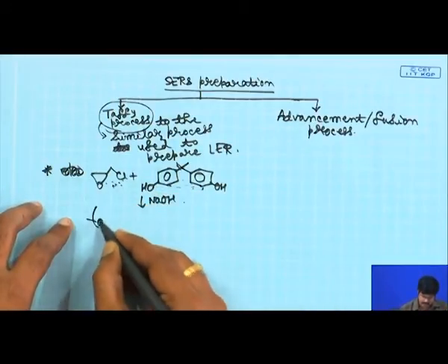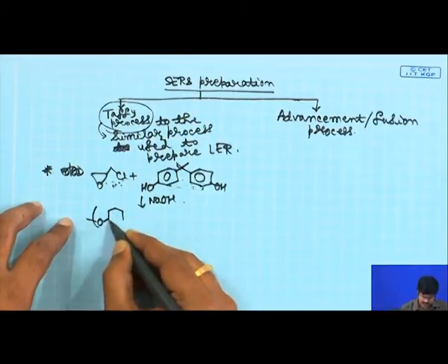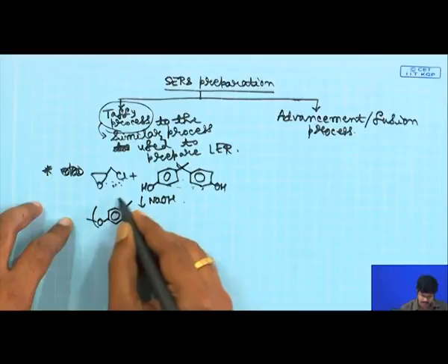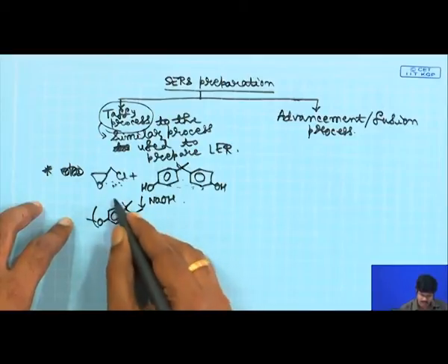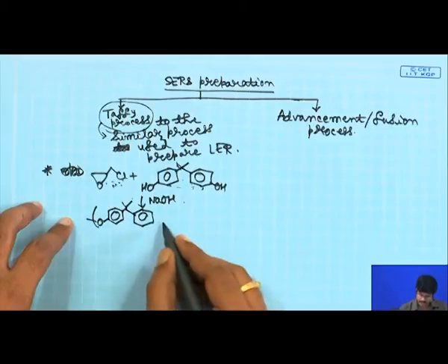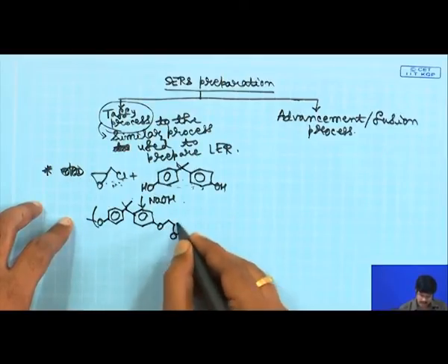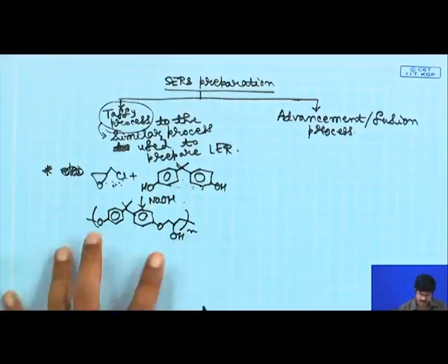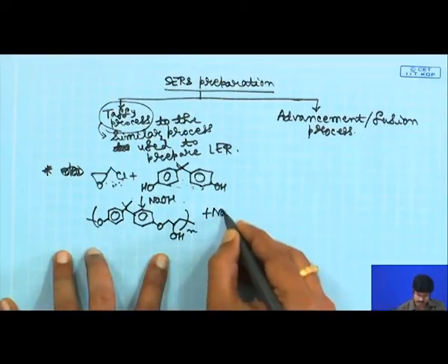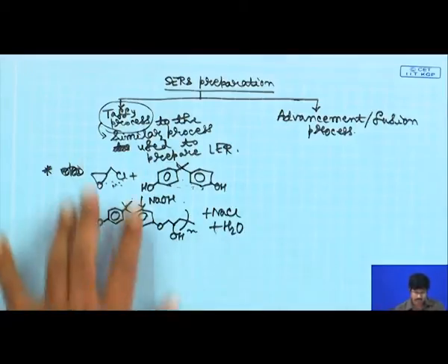So, you will get a product which is having a repeat unit like this. The methyl groups I am not writing down, but the methyl groups are there. So, these two bonds have methyl groups, and so this is your repeat unit. We have talked about this before, all right. And in the process your sodium chloride is formed and water is formed. So, taffy process is simply very similar to the process to prepare your liquid epoxy resin. Only difference is that for liquid epoxy resin you take close to 10:1 ratio of your epichlorohydrin to bisphenol A, and you are then reacting with sodium hydroxide.